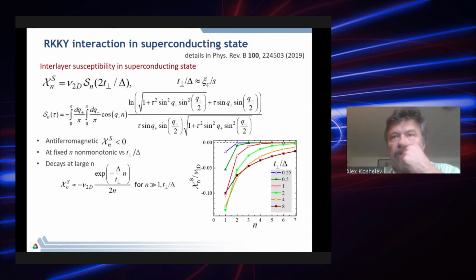Now I move on to the superconducting state. This is a result of derivation for the superconducting state. We obtain the interlayer susceptibility, which is a function of layer index, and some universal function of the ratio of the hopping integral divided by the gap, which actually approximately gives the c-axis coherence length divided by the interlayer spacing.